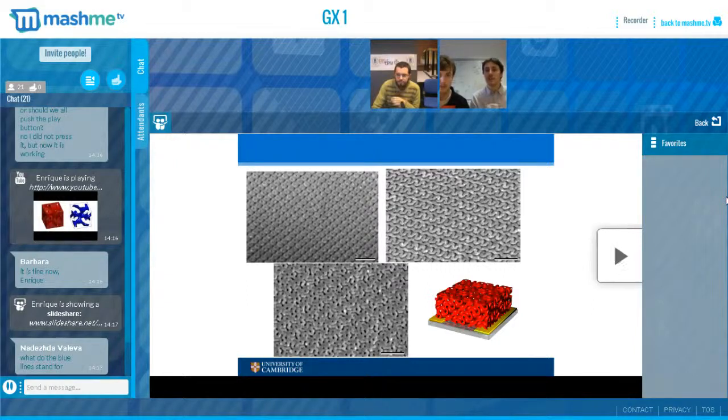And so the electron beam is reading through the whole image. It's just like the old TVs where you had your TV screen and there was an electron beam at the back writing the image all the time. So that's exactly what's happening in the electron microscope. You have a beam that reads across the sample, and for every spot where it hits the sample, the detector looks at how many electrons are coming back. So the brightness depends upon the material that you're scanning and the topology it has, so its shape, and that's how we use it to measure the nanostructure.